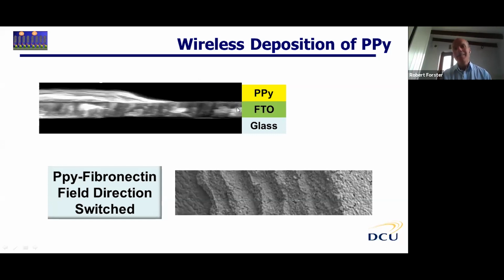What's interesting is that this end of the electrode - we're looking at distance along the electrode here, about 1 centimeter when doing the deposition - but the potential is varying during the deposition across this surface. Here's the transition between the non-polymerizing and the polymerizing zone, and in some sense we're actually mapping the potential distribution along this electrode surface. What's really interesting is that this transition is actually quite sharp - you go from no deposition to essentially Nernstian controlled or kinetically unlimited deposition within something like about 300 nanometers, quite a lot sharper than we'd imagined. So there are influences of mass transport as well as the potential distribution going on there.